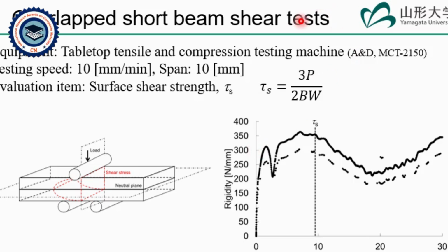This principle and the fact that stiffness decreases considerably as the materials yield are used to find the stress required for the surface of the molded product to begin yielding in shear. The tests were conducted using a tabletop tensile and compression testing machine with a span of 10 mm and loading speed of 10 mm per minute. The shear stress was obtained from the obtained load deflection curve using this equation.